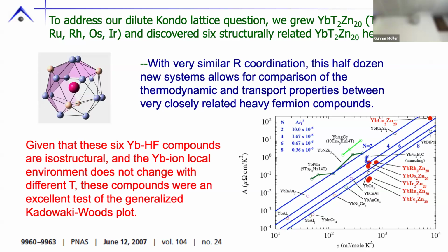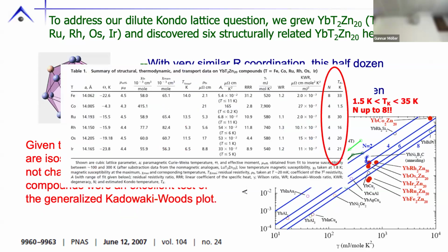If you want to think of it, what I'm doing here is I'm not changing my CEF splitting of the ytterbium much, but I'm changing my Kondo temperature. With a high enough Kondo temperature, I'm able to have it hybridize my full R log 8 before I've depleted some of my entropy by going through CEF splitting levels.